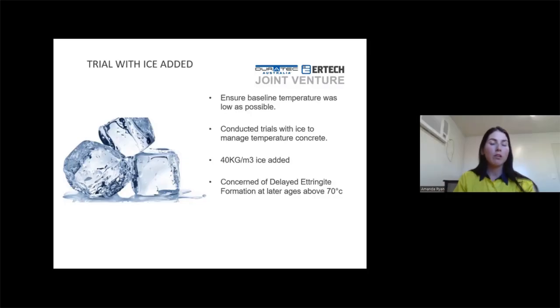I think it was a week of 35 degrees Celsius days. You have to consider all the materials that go into the mix: they are left out in the heat, they're not always covered, and they don't always have a water sprinkler on them 24/7. So sometimes the materials in the summer months are a lot hotter, a lot warmer, so you have to take that into account as well as the ambient temperature.